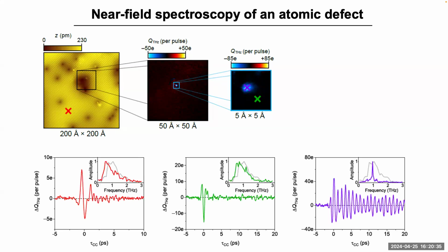Okay, now, if we measure these waveforms, we see in the pristine region some sort of interesting waveform. If we go to this green, we see yet a different pulse, but spectroscopically, they're not that different. However, if we put the tip on top of this bright blue dot, we see a very, very strong resonance. And so now this is the terahertz field that we measured just with the tip located there, which is 0.2 nanometers away, right? So this is orders of magnitude record in spatial resolution in terms of near field microscopy.